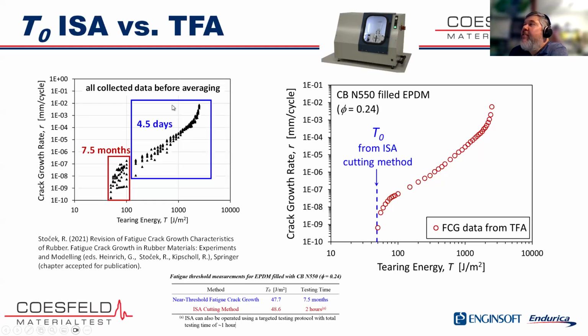Like in this case, we're able to measure the upper end of the crack growth curve in about a week, right? That gets us down to about 10 to the minus 7 millimeters per cycle, but you can't really see a threshold until you get down to about 10 to the minus 8 or 10 to the minus 9. And so just this last little bit of data on the curve takes about 8 months if you're going to try and use the direct method. So obviously much more efficient to run a 1 or 2 hour test than an 8-month long test.